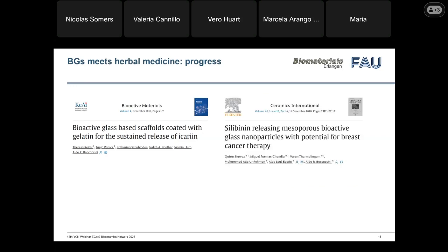And finally, here there is an example for cancer therapy. Silibinin has been studied as a tumor suppressor. Here they used mesoporous bioactive glasses, loaded them with this silibinin, and tested them again on breast cancer cells. Here they also showed a concentration-dependent effect. But the positive part was that the lowest concentration that they found had an effect is a much lower dose than that reported in the literature. So this was quite successful for them, and showed great potential for cancer therapy.